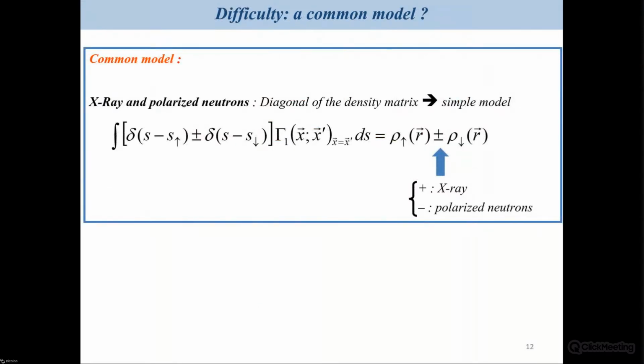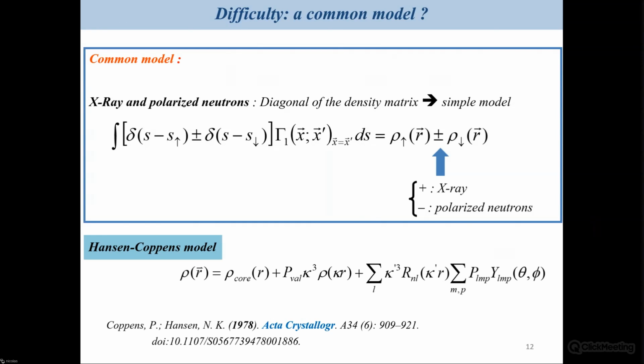If you speak only about X-ray and polarized neutron or neutron diffraction experiments, it concerns the diagonal part of the density matrix, which is of course the simpler case. In that case you can consider that, changing the sign from X-ray to polarized neutron, you can use the same model, and that model can be derived from the Hansen and Coppens model. I will rapidly remind you of the Hansen and Coppens model. It describes the electron density as a sum of three different terms: the core, which is frozen in our case, a spherical expansion model for the valence density, and an aspherical model, which is able to reproduce all the different aspects of the atoms in the different systems.